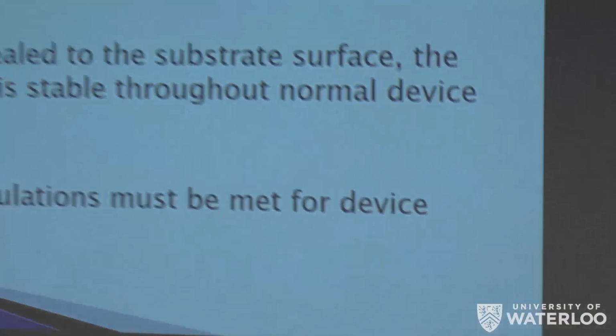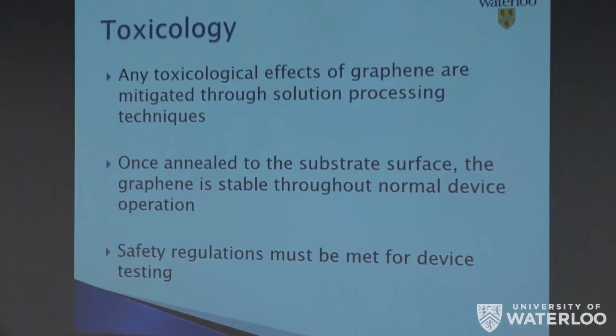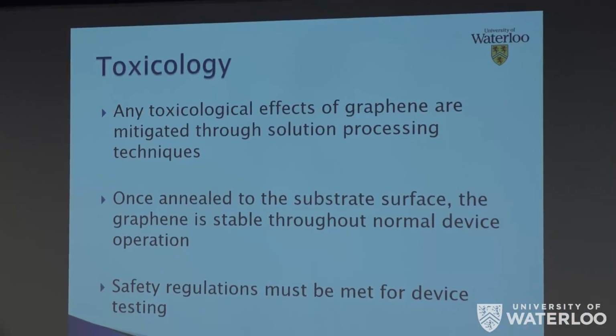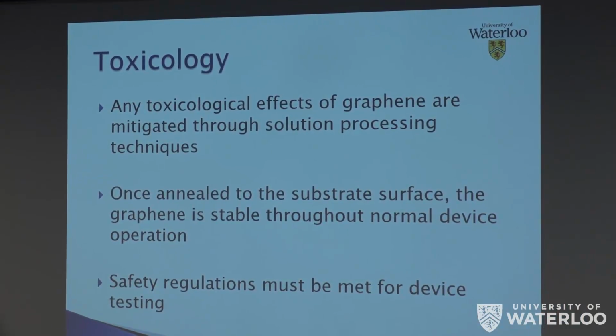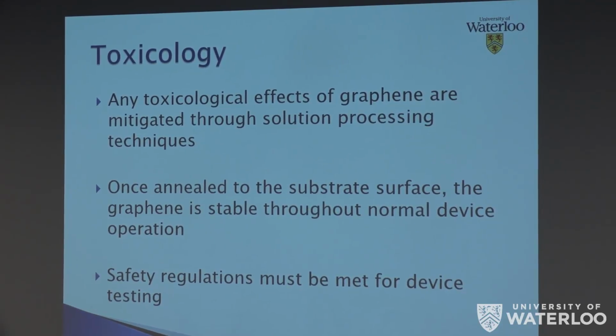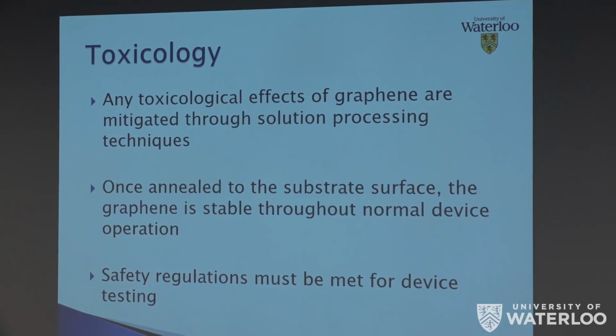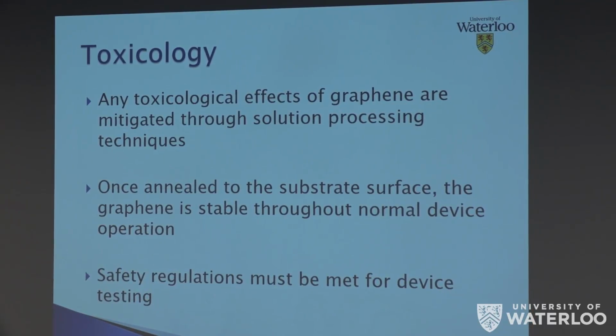The main issue with the use of any nanomaterials are their toxicological effects. Specifically, graphene in a powder form poses a risk to inhalation. To mitigate this risk, we designed our process so that it would be completely solution-based, and our aerosol deposition method would be enclosed to reduce the risk that graphene is aerosolized and would be breathed in. Once annealed to the substrate, by heating the substrate to 100 degrees, the graphene is stuck to the surface and does not pose an environmental or health threat throughout normal device operation.